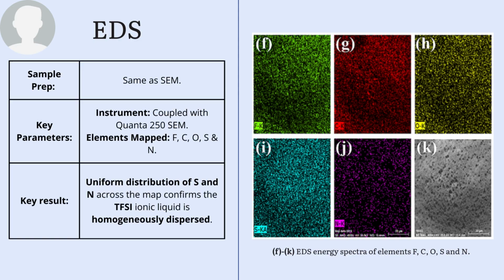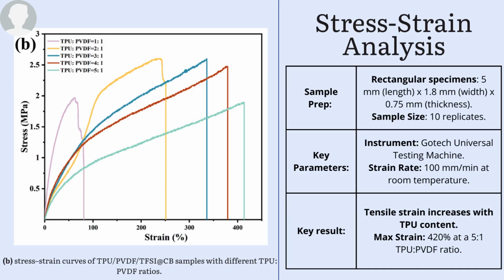The ionic liquid is evenly dispersed throughout the polymer matrix, ensuring that the ionic conductivity is consistent across the entire sensor area. Now, finally, to validate the material for potential wearable applications, tensile stress strain analysis was conducted using a universal testing machine. The standard rectangular specimens were prepared and stretched to the point of failure.